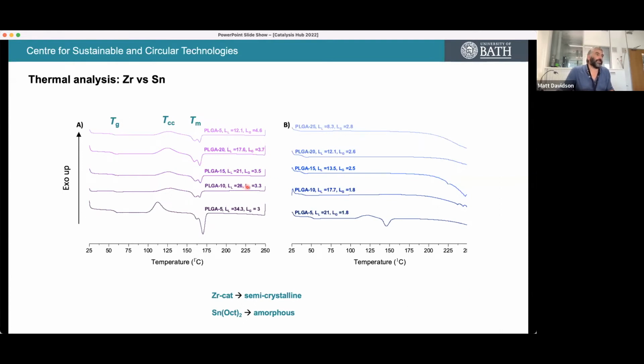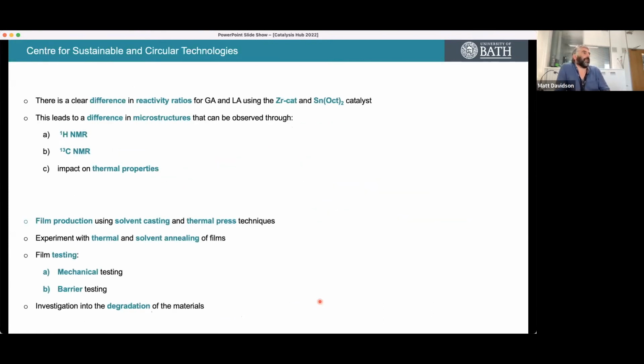And this has consequences for the material properties. As we go from 5% glycolide content to 10 to 15 to 20, and I think that should be 25, not 5 again, we see increasing crystallization of the lactide chain here. So with the zirconium catalyst, under the same conditions as we would have for the tin catalyst, the zirconium-catalyzed copolymer is semi-crystalline and the tin-catalyzed one is amorphous. That gives us some hint that the additional control that we have in the zirconium catalyst is really helping us here.